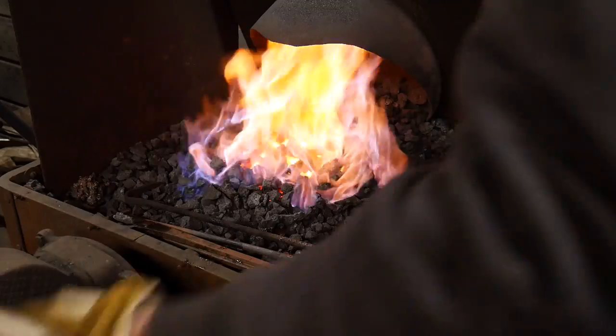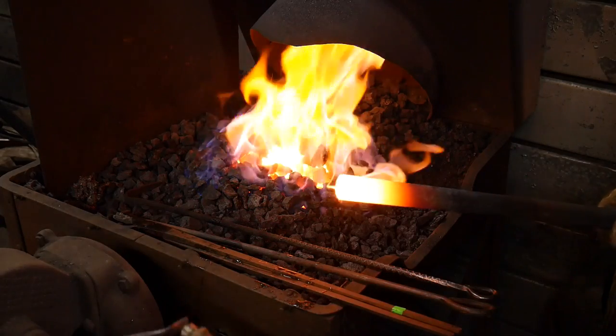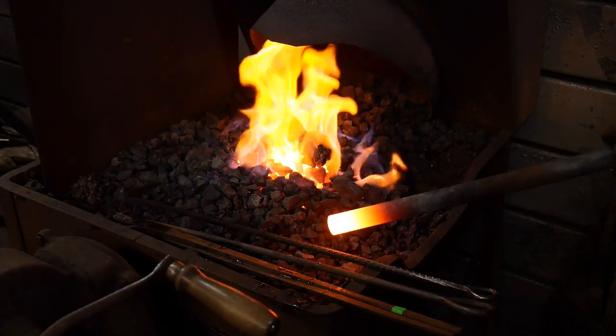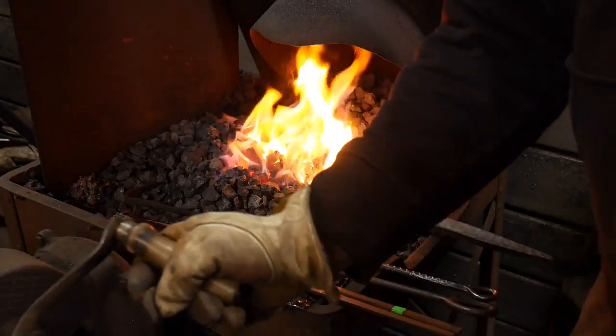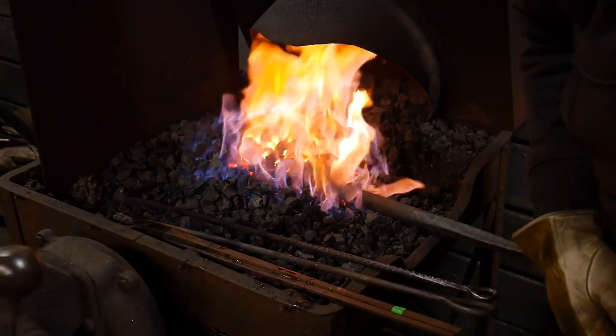It does snap quite a bit though. Not quite a sparkling heat, but still pretty darn hot — and within only about four minutes or so of it actually being in the fire. That is a really good forging heat, so four minutes for a one inch round rod. Yeah, coke's pretty awesome.